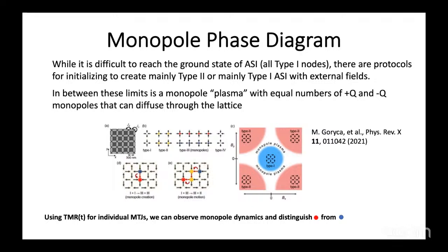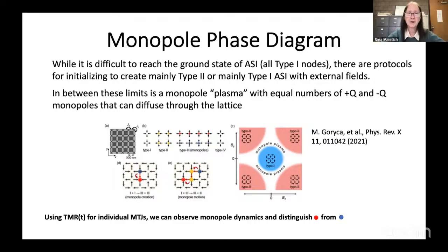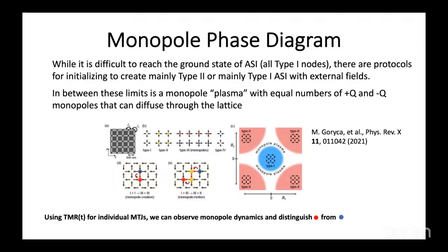Maybe the difference is because in this more realistic, so to say, spin ice, not in artificial spin ice, one has in reality real effective spins. Here you have islands, these small islands which work like spins, and their anisotropy is determined by their shape, right? As far as I remember, if they're circular, then it's the shape of these small islands, right?